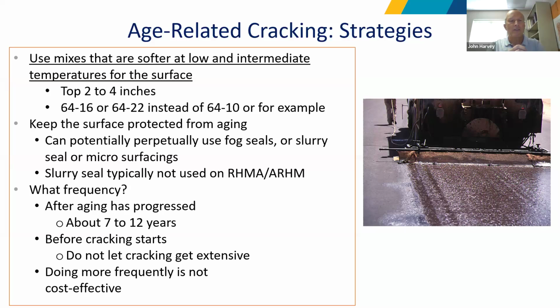So one of the ways to do that is if you're currently specifying a 64-16 or a 64-10 asphalt, if you go to a 64-22, that -22 means that that material is softer at lower temperatures. The -16 means -16 degrees Celsius, and you'll have the same properties at -22 that you had at -16 if you specify a -22. Keep the surface protected from aging.